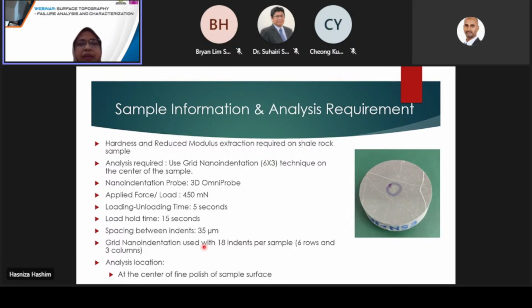Another study is where we did the testing on a shale rock sample. For this one, we are not using the 2D transducer. Instead, we are using the 3D OmniProbe because the sample surface is quite rough. The testing requirement is a force that is more than what can be offered by the 2D transducer. Since this is a bulk analysis, it requires a force of 450 millinewton, and the loading and unloading time we set at 5 seconds, with the hold time increased to 15 seconds.